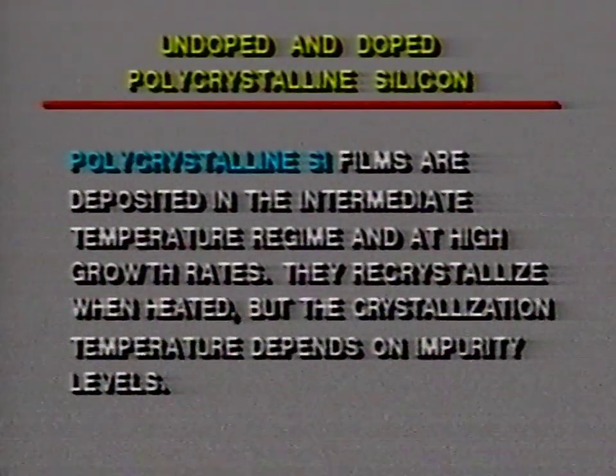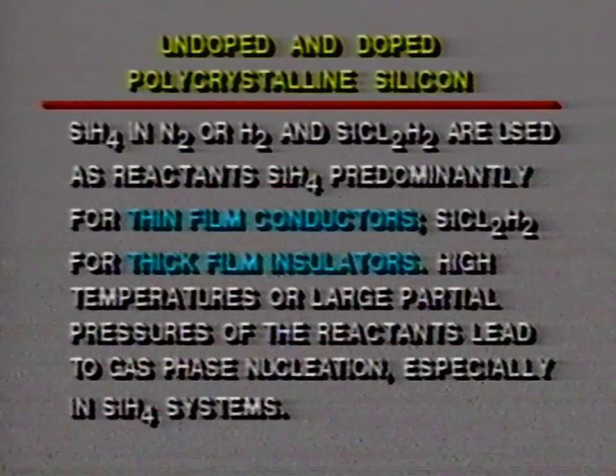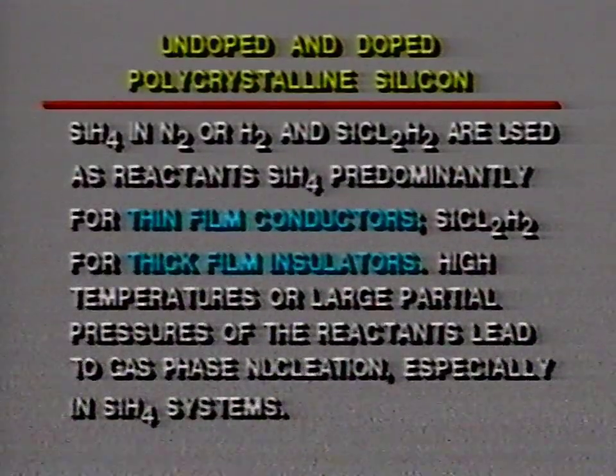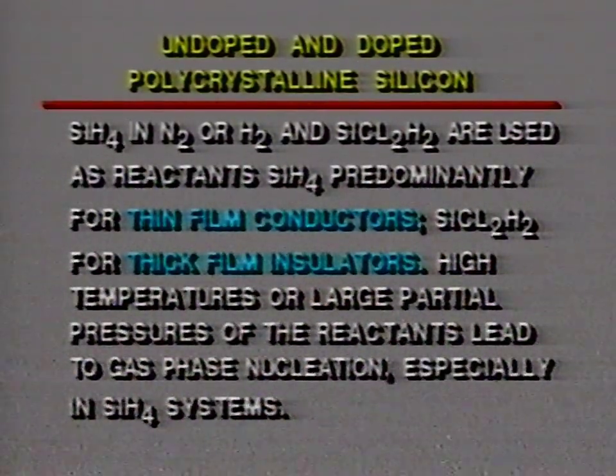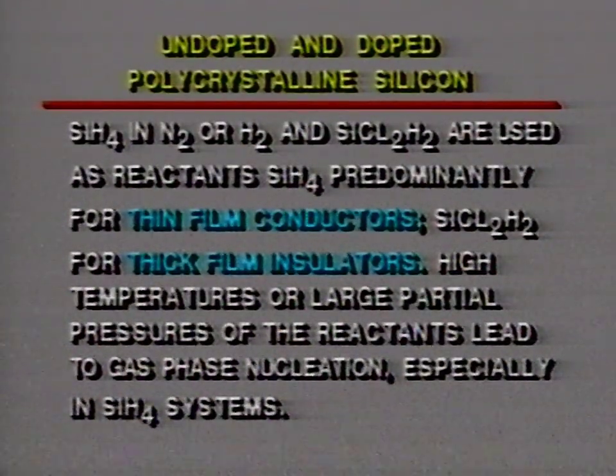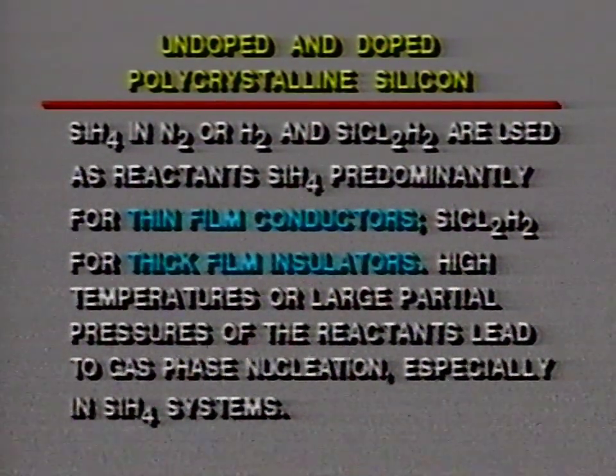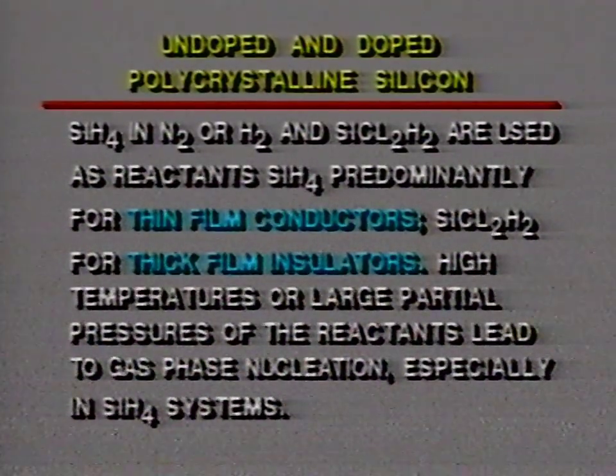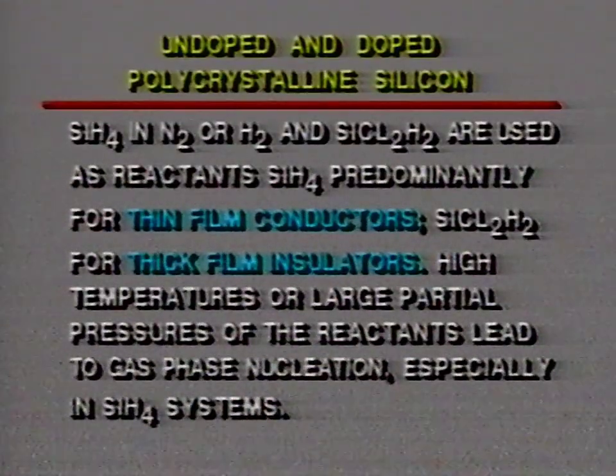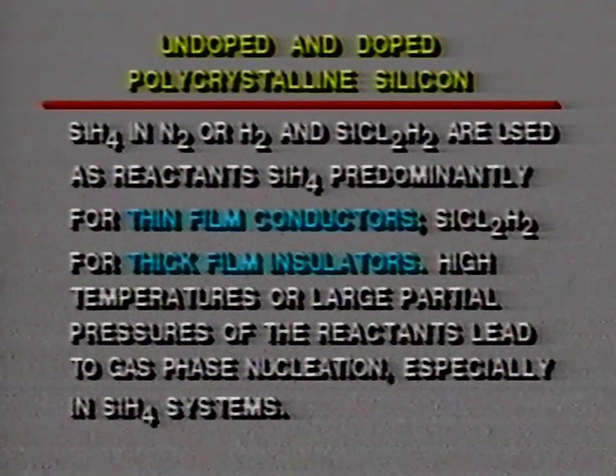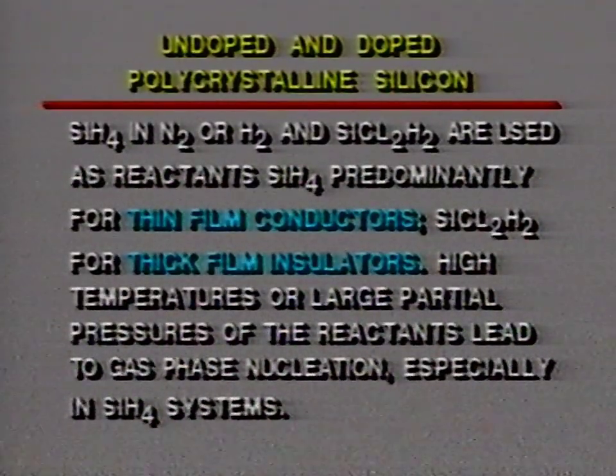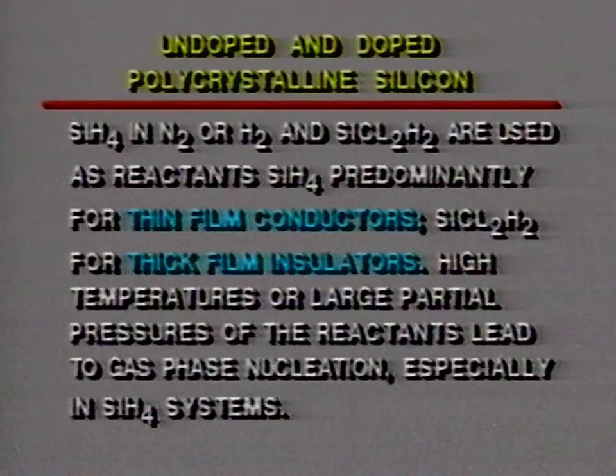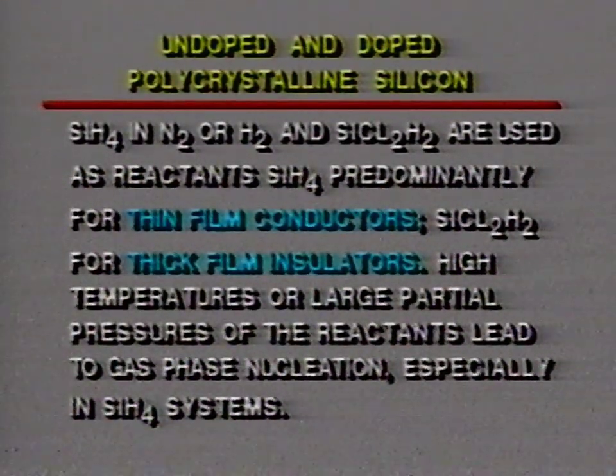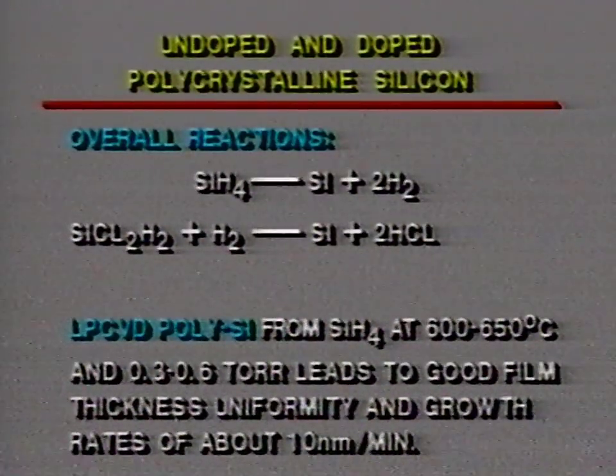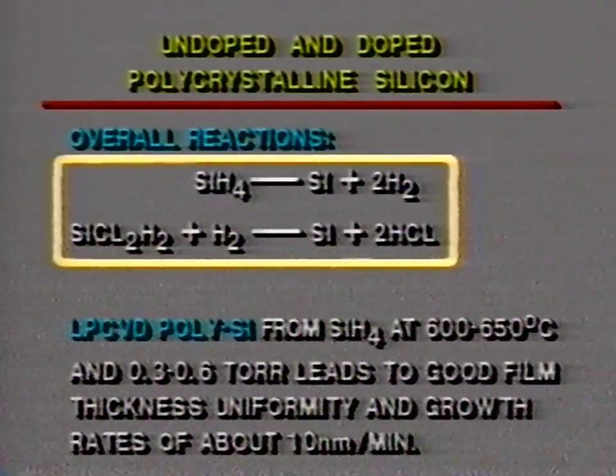The second point here is that silane in nitrogen or hydrogen and dichlorosilane in hydrogen are used generally as the reactant species, mainly for applications in thin film structures. Now, this dichlorosilane is used for thick film applications, where we have essentially intrinsic polysilicon that acts now as an insulator. And the high temperatures or large partial pressures of the reactants lead to gas-phase nucleation, especially in the silane system. So we have to be very careful to avoid that type of defect formation. The overall equations of the formation of silicon from silane and dichlorosilane are listed here.